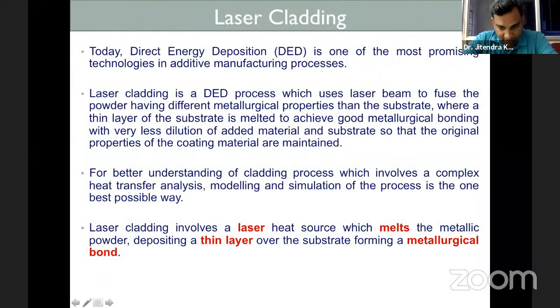So the last part of my talk is now we move to laser cladding, and this is the work I have used in my work. In that, I made the coating by laser beam, spreading the powder, and the laser beam travels over it, melts and solidifies it, and you can generate a thin layer. But the problem in laser cladding is distortion and dilution. If you optimize the parameters, then you will not get these types of defects over the surface. Otherwise, distortion and dilution are the biggest defects in laser cladding.